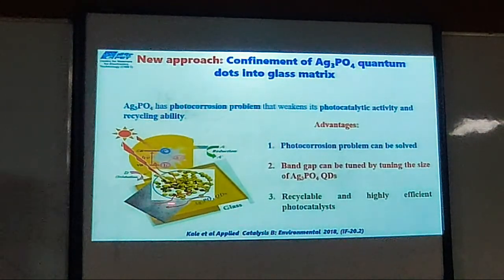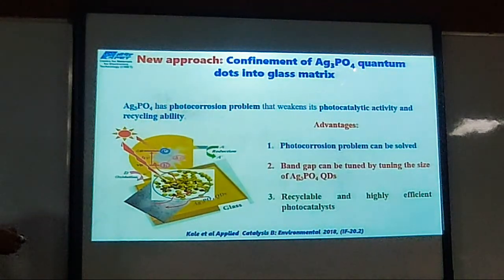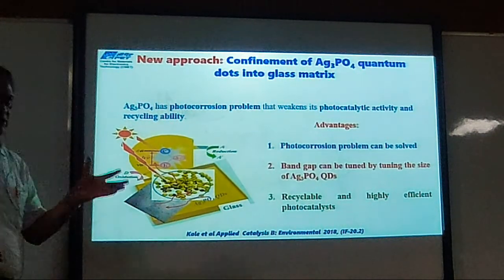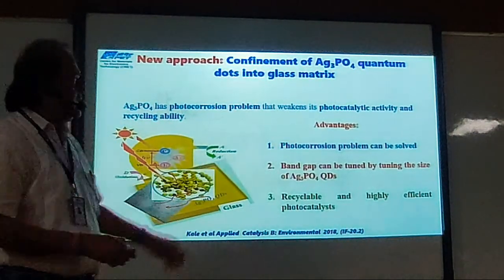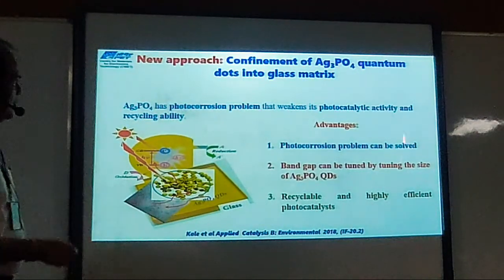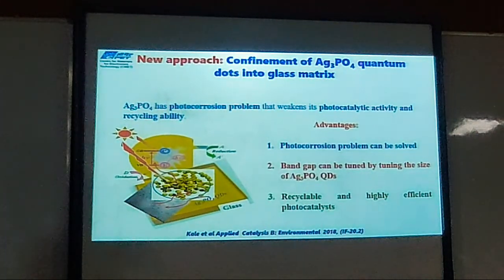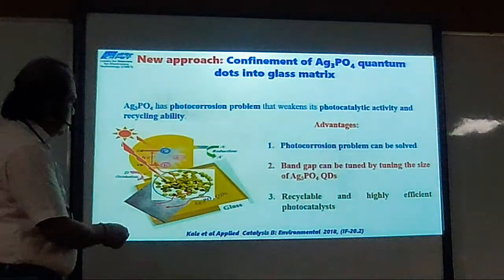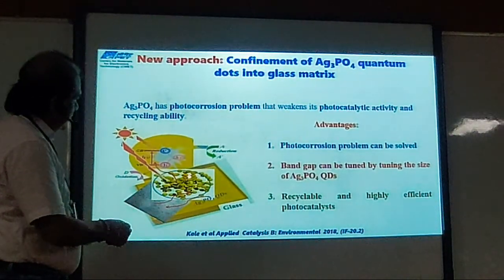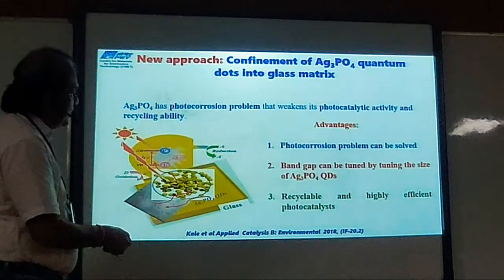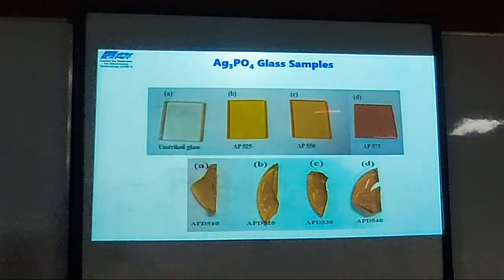Then instead of sulfide, whether we can have Ag3PO4, which is a very, very well-known photocatalyst for hydrogen evolution. But the problem with this Ag3PO4 is that it decomposes. When light falls on it, immediately silver and phosphate get separated. So we thought whether we can grow it in this glass, and we have grown this Ag3PO4 and they are highly stable. You can see they are highly stable in the glass.